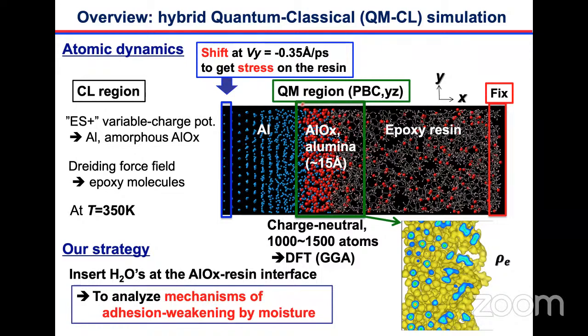Because we use a hybrid method, this central green region is taken care of by the DFT, the electron-level simulation method. Then the left and right end regions are taken care of in the classical way. I mean that the classical force field is applied to the resin regions. The aluminum region here can be taken care of by the classical ES plus variable charge potentials. This is famous for being able to describe pure aluminum and also amorphous aluminum oxide. Then this green region is taken care of by the DFT. Our idea is that we insert water molecules between the surface aluminum and the epoxy resin, and in these regions water molecules are inserted. Then we get the idea of the chemical reactions.